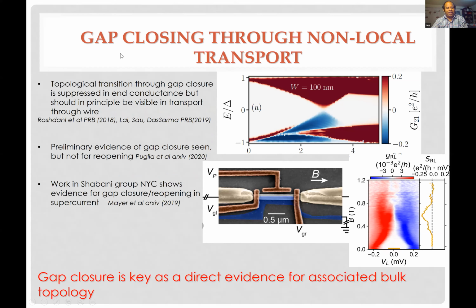So we need some way of understanding that the bulk properties have changed, not just the end. So one idea proposed was to look a little bit like the setup that David was alluding to, transport of electrons across the wire itself. And what you would see there is you necessarily measure the bulk gap, because the only way for an electron to go all the way across is for the bulk gap to close. And so you get a bulk gap closing and reopening. And this is the theory plot.